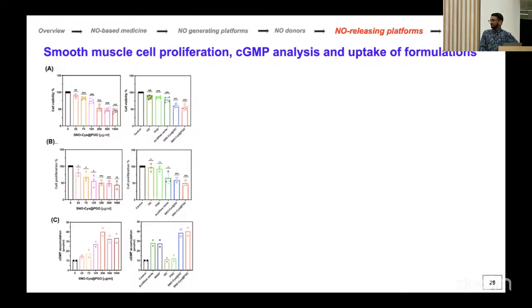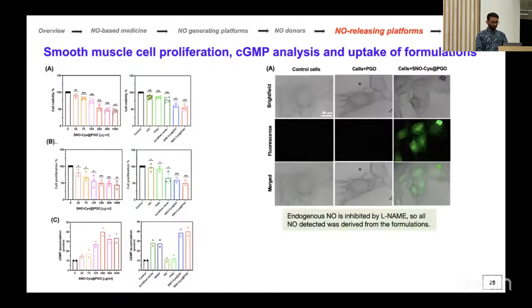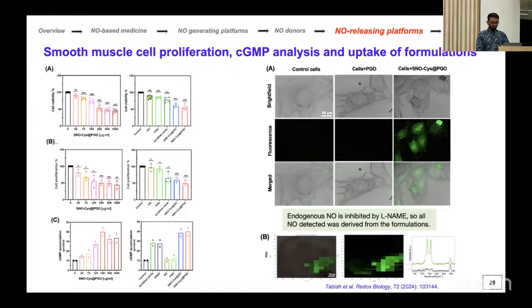And we see that with these formulations, in comparison to the unconjugated one and also acidified nitrite as a source, there is an increase in cyclic GMP. So that is the same story as before, because of the uptake of nitric oxide, the localization of nitric oxide in smooth muscle cells, and also the Raman imaging mapping to show the graphene uptake by smooth muscle cells.